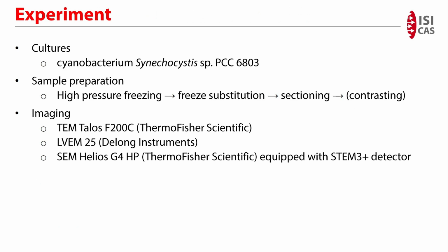So, for the experiment, the cells were fixed using the high-pressure freezing method, followed by freeze substitution in a solution of 1.5% osmium tetroxide in acetone. Samples embedded in EPON resin were then sectioned and either left unstained or stained using uranyl acetate and lead citrate. Sections were then imaged using three types of microscopes: high-voltage TEM Talos F200C, low-voltage TEM with STEM mode LVEM25, and SEM Helios G4 equipped with a STEM detector.